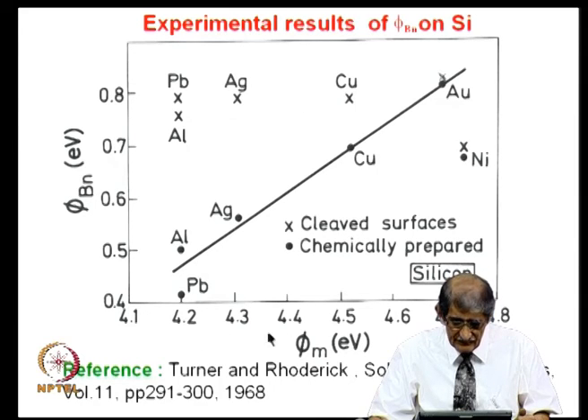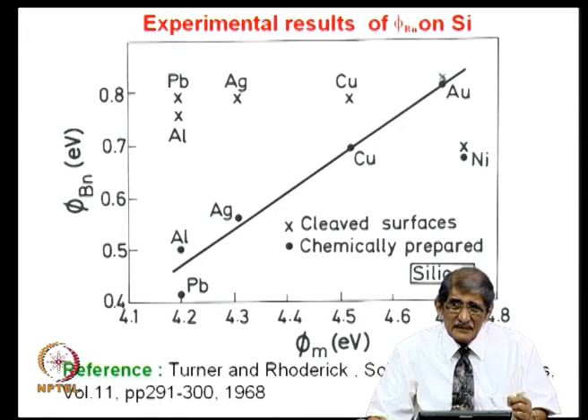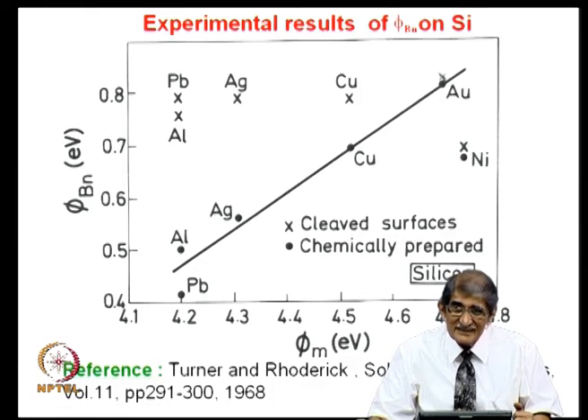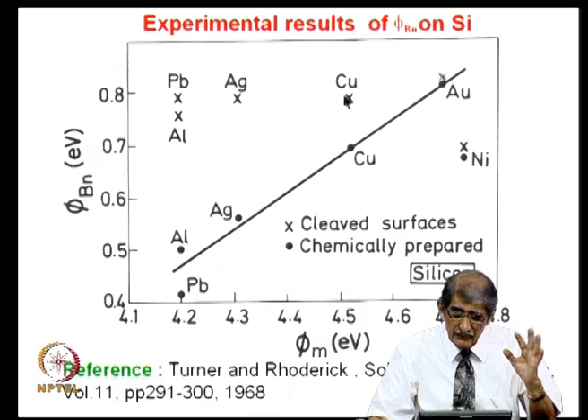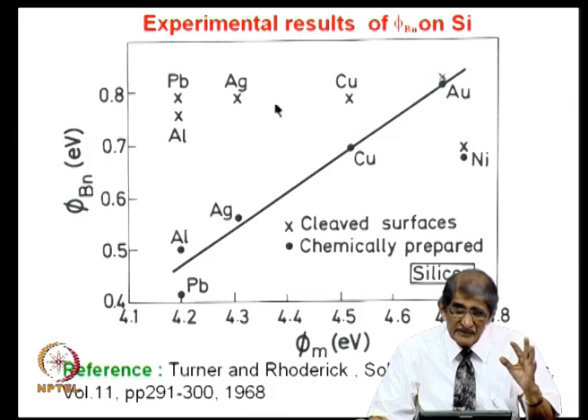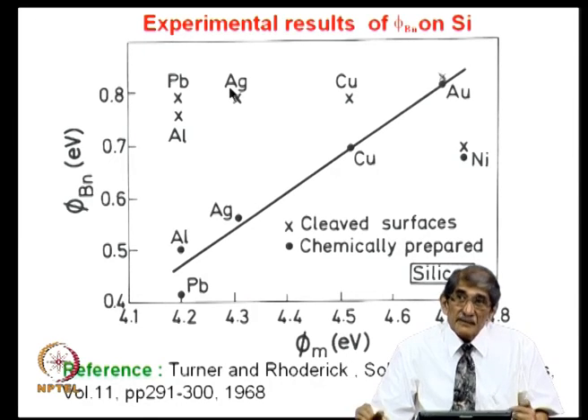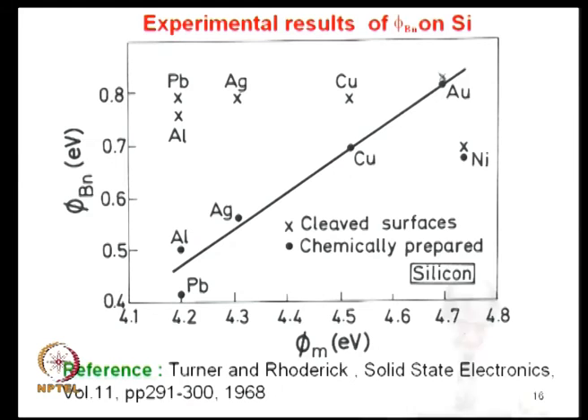Absolutely, see, on the x axis you have the work function corresponding to aluminum, silver, copper and gold, all these cross x. So, the phi b n is about 0.8, almost about 2/3 of E g. That means once you have fixed the E g for silicon, that was fixed, okay, that is freshly cleaved. But it gives a clue that there are large dangling bonds, the surface states, which were responsible for this. So, if you are able to remove those, then you are in business.